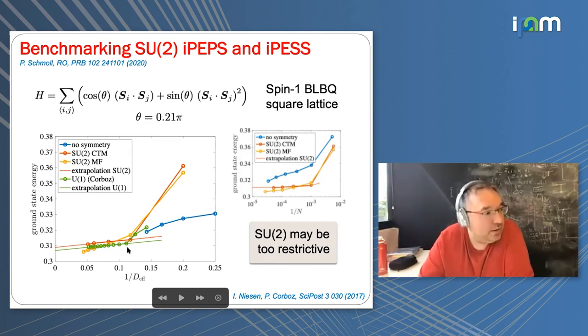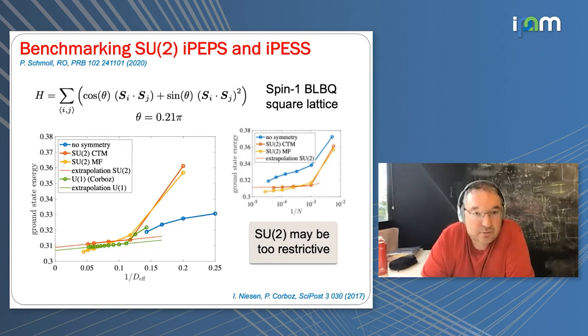That's fine. So the first conclusion that we see here is that the U1 symmetry is giving slightly better results, in terms of lower energy, than the SU2, okay? And this was very surprising to us.